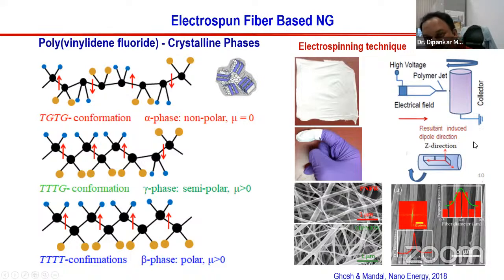As I discussed in the electrospinning process, you see this is the polymer nozzle and this is the collector, and one has to apply an electric field between the tip and collector. Here you apply the force through the syringe pump. Then you have a Taylor cone formation and fiber. Now you can design your collector in different ways, like a drum. If we want to make aligned fiber, we use a higher RPM. Then you have this one, right bottom side, aligned fiber.